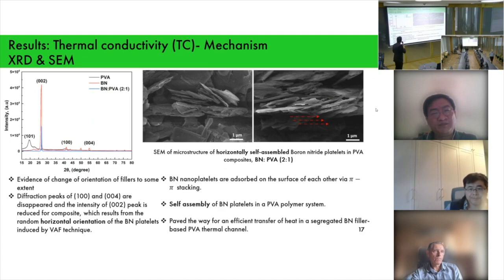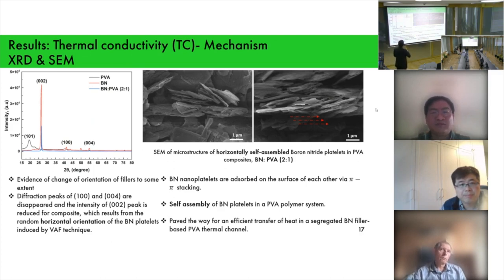Yeah, here, Professor, you see that this is the peak for the pure PVA, like you commented before that I have to mention it. So this is the diffraction peak for pure PVA, whereas for pure BN, you see diffraction peaks at 100, 004, and 002. So when you have the segregated structure of BN PVA with more BN content, there is disappearance of these diffraction peaks to some extent. And you see that there is a slight orientation to some different orientation by using the self-assembly. So even though our system is a segregated structure of PVA and BN, you might not see the peaks of PVA inside the BN composite system, but it still shows the disappearance of the peak, which we can say indicates that there can be orientation of these BN platelets in the horizontal position.